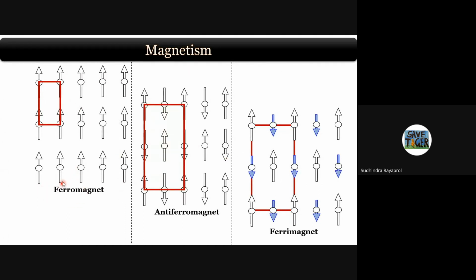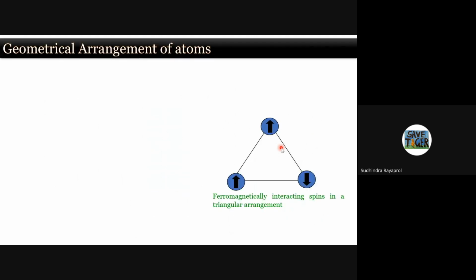But if you look at the structure, if you look at the dimensions, you have a ferromagnet. By definition, we say that all the spins are aligned in one direction and the magnitude of all the spins is the same. In the case of antiferromagnets, the magnitude of spins is the same, but the spins are aligned opposite to each other, right? So if you want to draw a magnetic cell, you have to go to the spin up portions. You can see that it has to travel a lot compared to the ferromagnet. However, in the case of a ferrimagnet, you have a superstructure reflection, which means you have spins which are anti-parallel, but the spin moments are not of the same magnitude. So you can consider a ferrimagnet as a special case of an antiferromagnet. But the difference lies in the unit cell dimensions, and I will come to that.